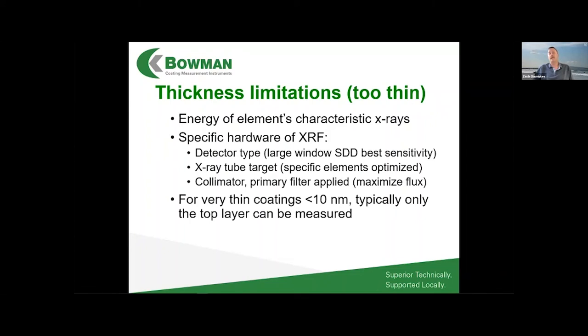The X-ray tube target is important because we can choose the anode type based upon the application we're trying to measure, if it's something really thin. Our typical tube target is tungsten, just because it's a good general purpose target and a robust tube. But we can use other things like chrome, rhodium, or moly if somebody is looking for specific application sensitivity. And then there are the collimators, which control the spot size, and the primary filters that we apply, which go between the X-ray tube and the sample. Depending upon those, that'll control the ability to measure a thinner coating.